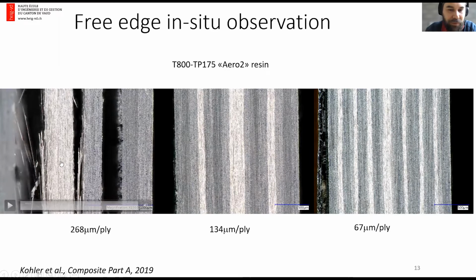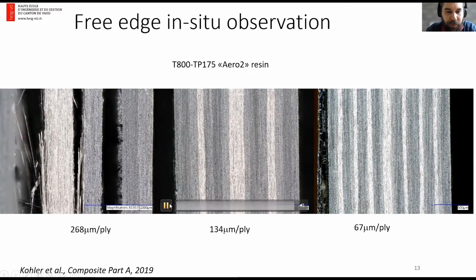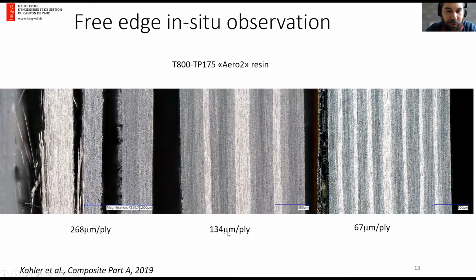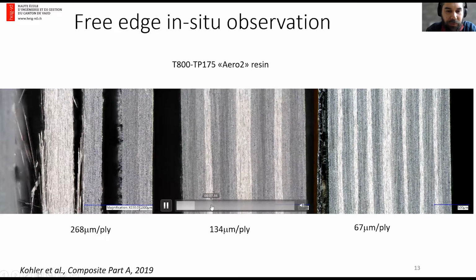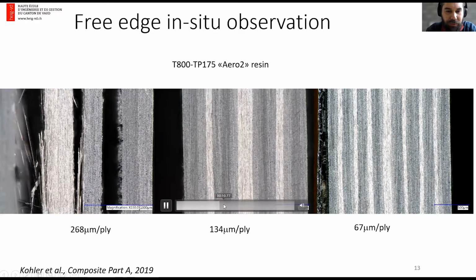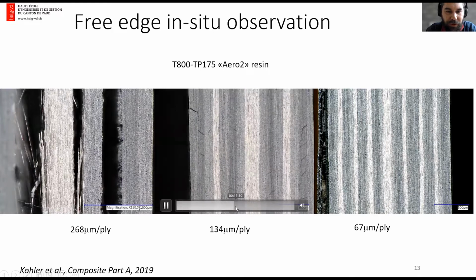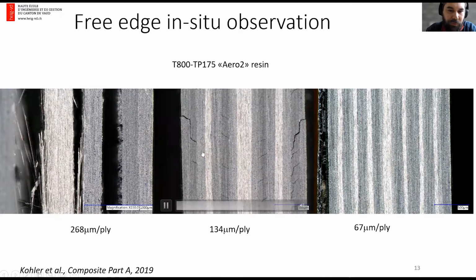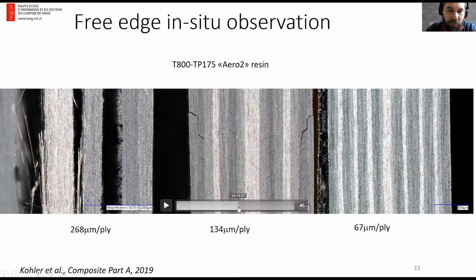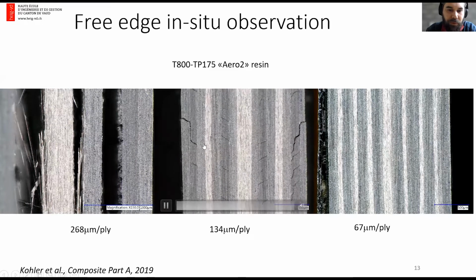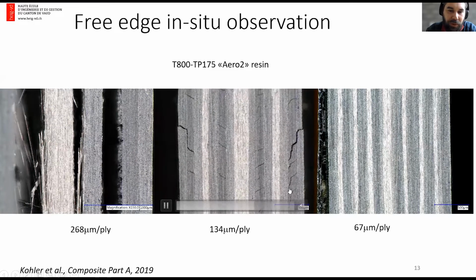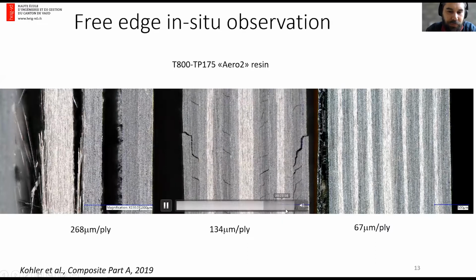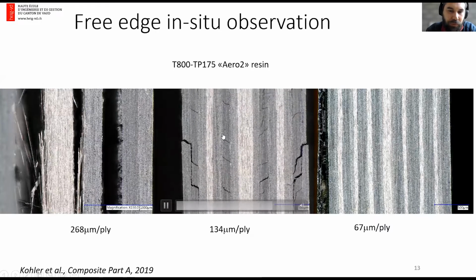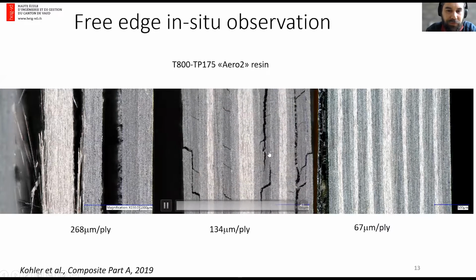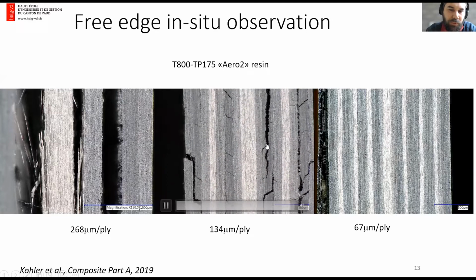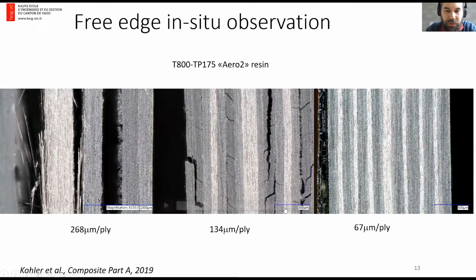All the other plies are, let's say, fragmented. For an intermediate ply thickness, so 134 micrometer per ply, we can see that most of the test there's not much happening. And here at about 50% of the test, we have the appearance of the first transverse cracks, but very limited delamination. We have a higher density of transverse cracks that develops, and finally some intralaminar cracking and delamination close to the end.